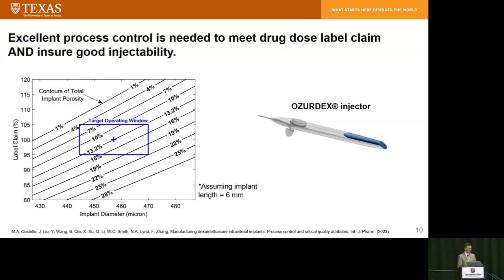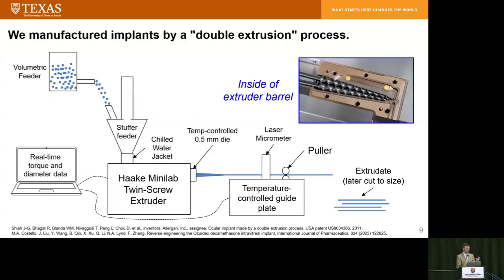So let me go back to the previous slide and mention this again. The key to the process control is measuring the torque and having a consistent torque in the extruder, because that leads to consistent melt pressure, and then the melt can flow through the die at a consistent rate, meaning that it's then pulled to the correct diameter at a consistent rate. So yeah, that's the essence of this process, is achieving a steady state.